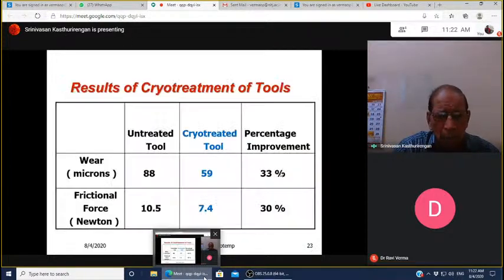Well, by this cryogenic treatment, you can see the tool steels, for example, have improved their performance. Some results are shown here. For example, the wear in microns, untreated tool is about 88. Well, I don't know the units, let's say some units. When you cryogenically treat it, the value goes down to 59. That means the tool is now better. So there is a performance improvement on the tool of almost about 33%.